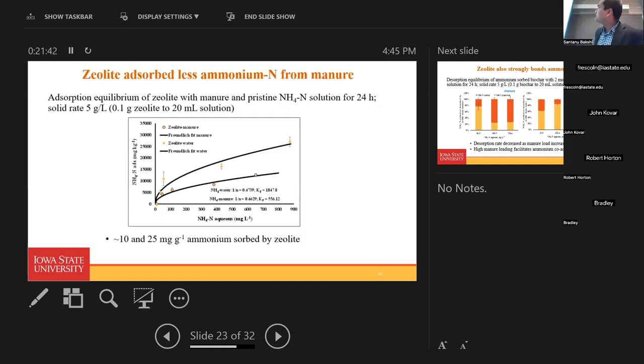Now the zeolite adsorbed less ammonium nitrogen from manure, because zeolite has only the cation exchange positions to get the ammonium from the system. So we obviously get less ammonium nitrogen from the manure. We have done the experiment in the same condition, 24 hours, and the solid loading is 5 gram per liter. Around 10 to 25 milligram per gram ammonium was absorbed by the zeolite, but it is less than the biochar. Biochar absorbed some ammonium and zeolite absorbed some more. If we sum up biochar and zeolite, the total ammonium would be very high.